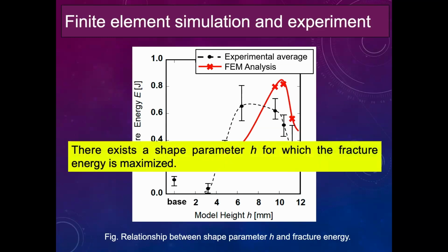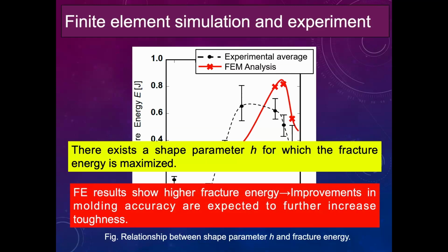But from this, we can say that there exists an optimum shape parameter H for which the fracture energy is maximized. In the experimental data, the fracture feature was quite different between the FEM and the experiments. In this case, in the experimental data, the maximum value of the fracture energy was taken at 8 millimeter of the shape parameter H. The FEM results show a higher fracture energy from this curve comparison, but improvements in the molding accuracy of the sickle joint in the CT specimen are expected to further increase fracture toughness.